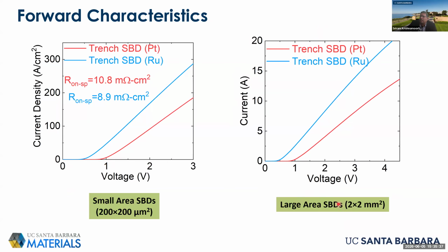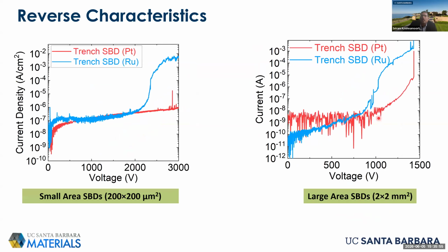And we also made large area diodes. These are 2 by 2 millimeter diodes that are relevant for power electronics. So essentially here we were able to measure on wafer currents up to 20 amperes in a 2 by 2 millimeter device using ruthenium as a contact. And what is outstanding is that the reverse leakage in these devices is close to noise floor, at very low values.